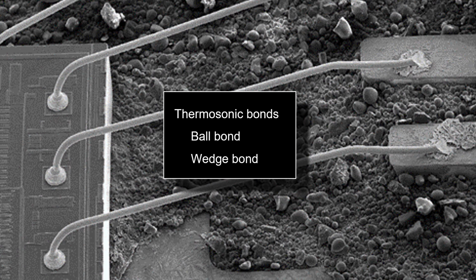There are many different wire-to-pad pairings. Most wire bonds used today are thermosonic bonds, either ball, wedge, or both. The background is a scanning electron microscope image of a decapped silicon integrated circuit. On the left, we see gold ball bonds to aluminum pads on the die, and on the right, a gold wedge bond to a copper trace on the package.